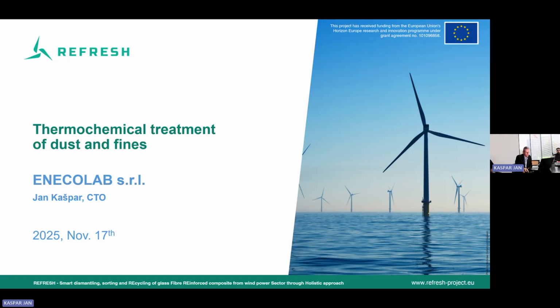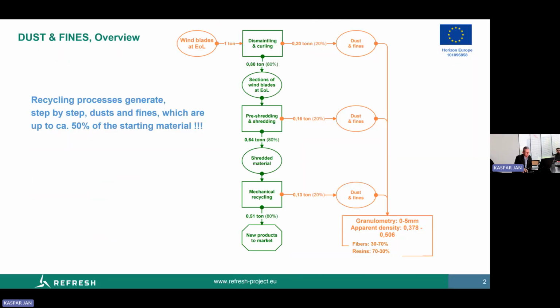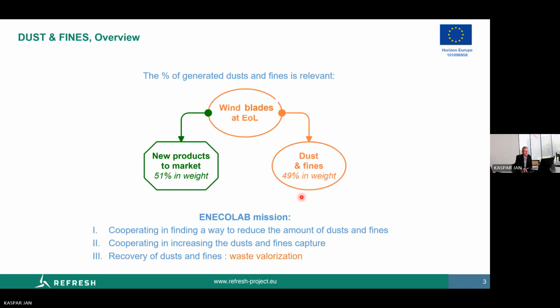The point is that within our project, when we start from the wind blade, we find that there is a lot of production of dust and fines in every part of our processing, which means that up to 50% of the starting material is essentially material which is difficult to trade and which needs to attain some valorization.